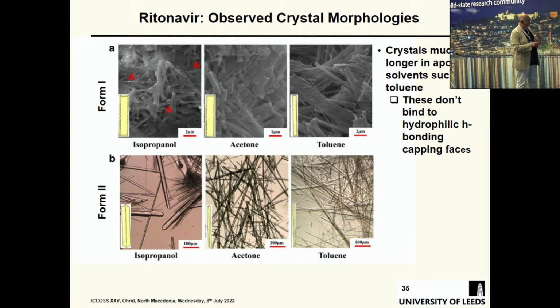It hates the ends of the crystal because they're hydrophilic, and the crystals shoot out as long needles. That effect is less if you take a protic solvent. The protic solvent will love the ends of the crystal because that's where all the hydrogen bond donors and acceptors are. And lo and behold, you get quite chunky crystals. So the basic principles of molecular recognition enable you to get the crystals that you want. The other thing, if you're a bit geeky like me, I've always been interested in polar crystals. You can see the effect of a P21 space group. You get these sort of pyramidic type crystals pointed at one end due to that polar nature.